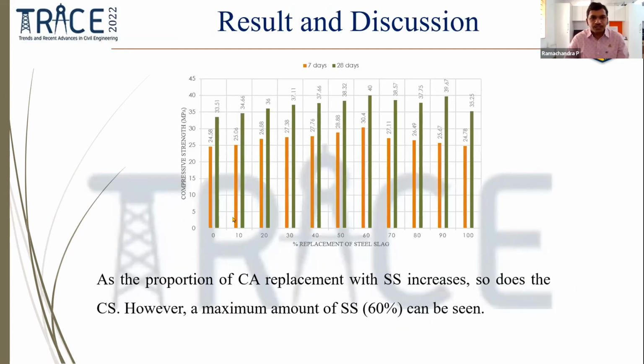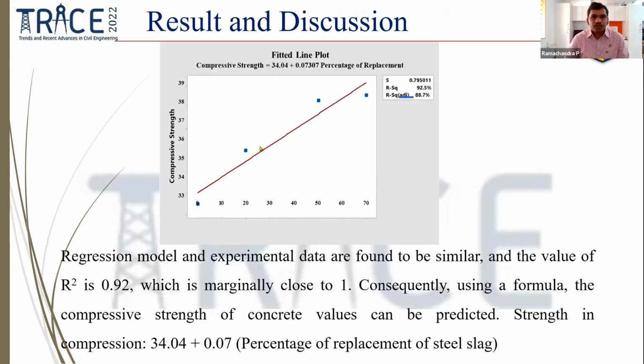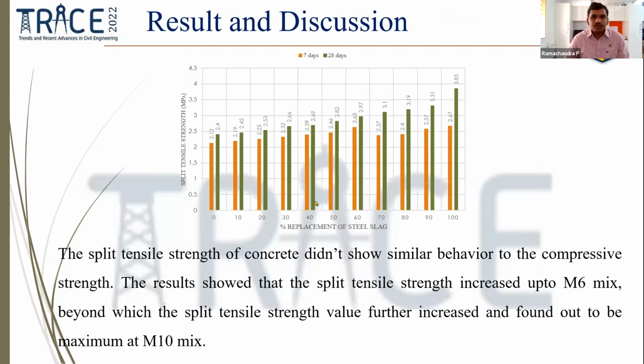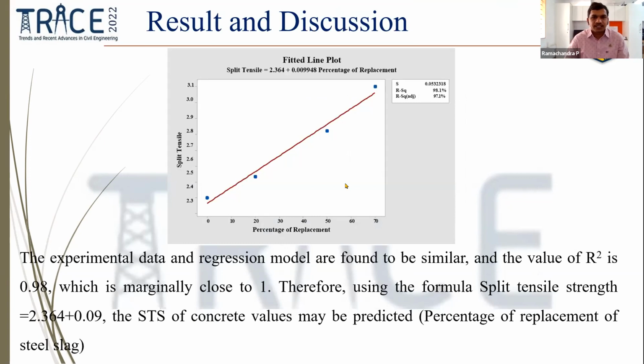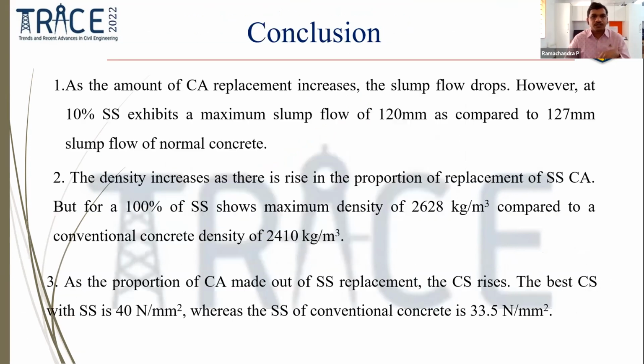So next is the compressive strength. Compressive strength also keeps on increasing with the percentage increase in the steel slag, where you can see the 60% of steel slag which has been used has given good strength. So this is the prediction value for the compressive strength. And coming to the split tensile strength, we got good tensile strength for the 100% replacement. So these are the results for the split tensile. Basically this Taguchi method uses the fitted plot curve where exactly we can simulate or predict the results of these particular conclusions.